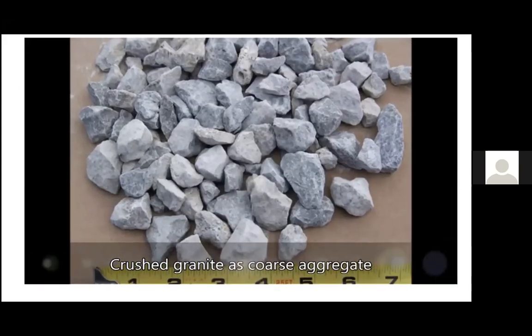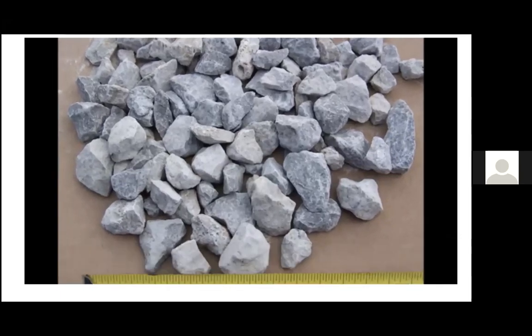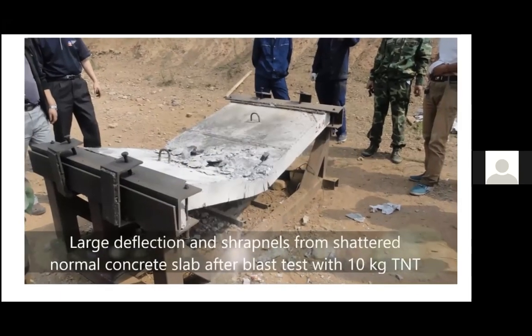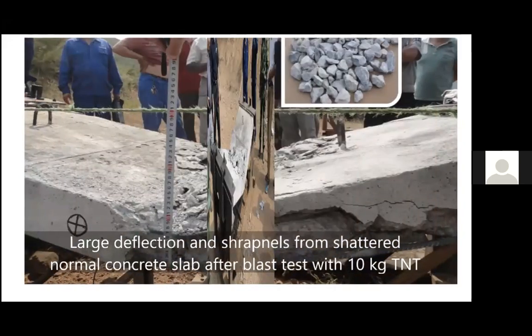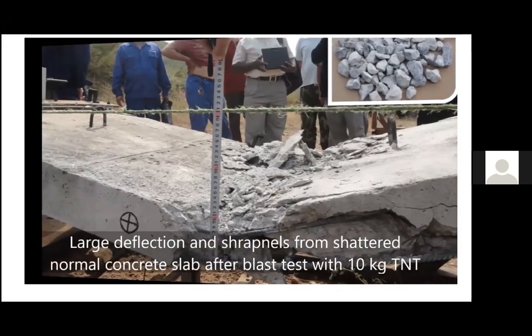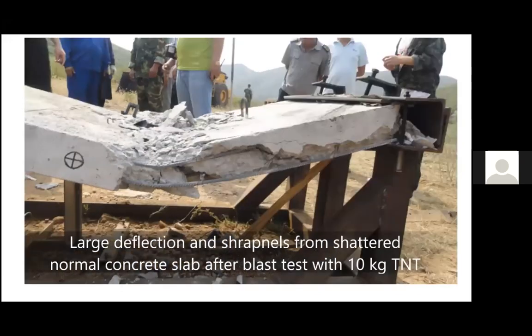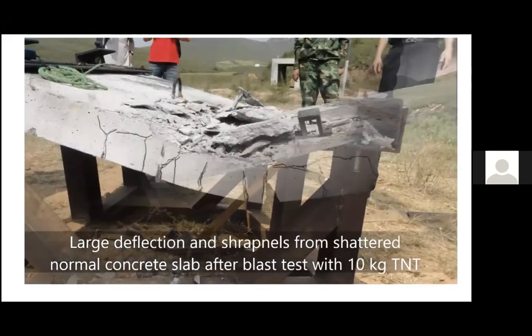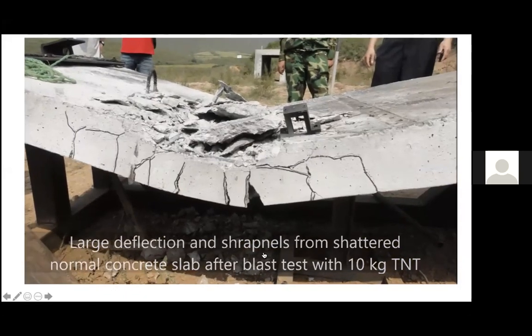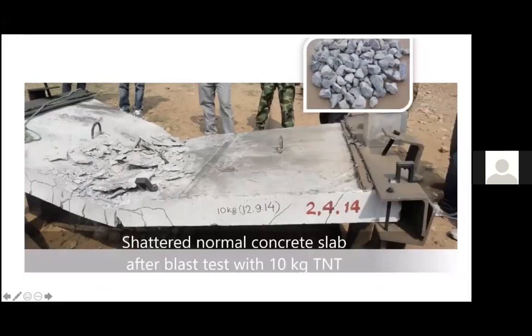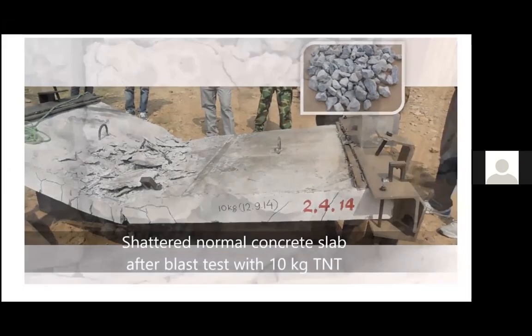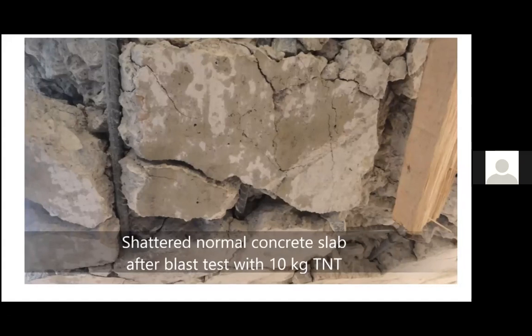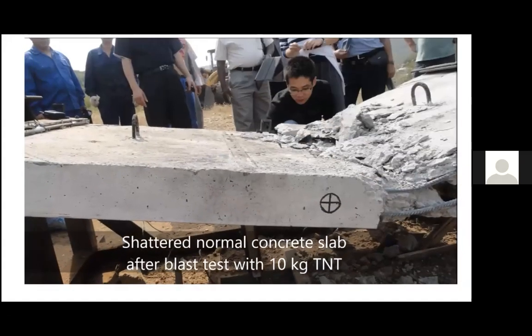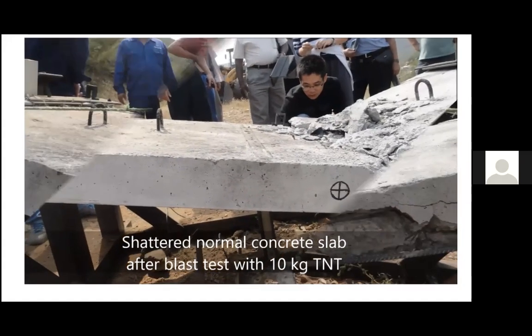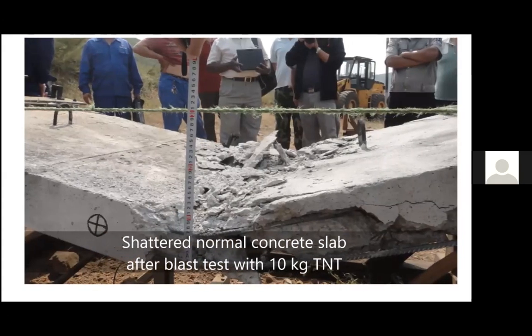So we did two slabs. One is the normal weight aggregate slab. That one almost shattered after the test. It couldn't withstand any of the impact or blast, because you see the exposure of the steel and a lot of shrapnel. These are the shrapnel. And the slab becomes unusable. You couldn't expect anything from the slab after the damage done to it.